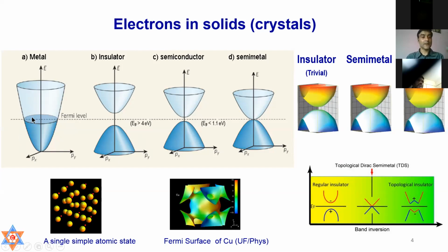Similarly, if we go to sub number B, what we understand clearly is that there is a gap between this band, which is called the empty or the conduction region, and the occupied region, which is the valence region. There is a gap of the order of 4 electron volts, which means the gap size is really very large, indicating that this is an insulator.